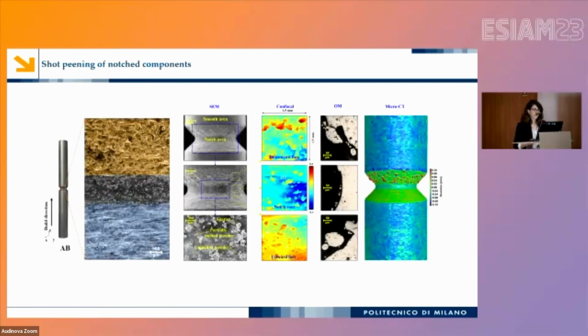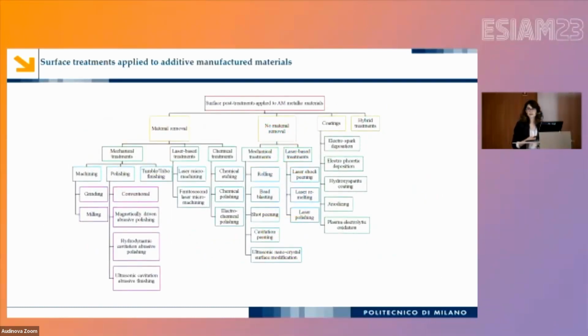Here you can see different imaging technologies, optical microscope, micro CT, and scanning electron microscope images, that we took in order to show how inhomogeneous the surface roughness is as we change the build direction with respect to the surfaces of the part. To enhance and homogenize the microstructure, different methodologies are suggested in the literature as post-processing surface treatments for additive manufactured parts. We have grouped them into subtractive, non-subtractive, and coating technologies.